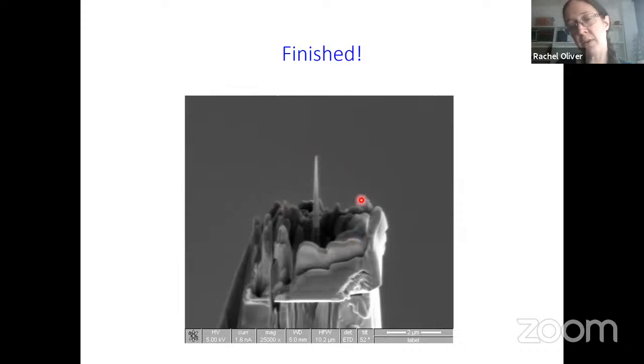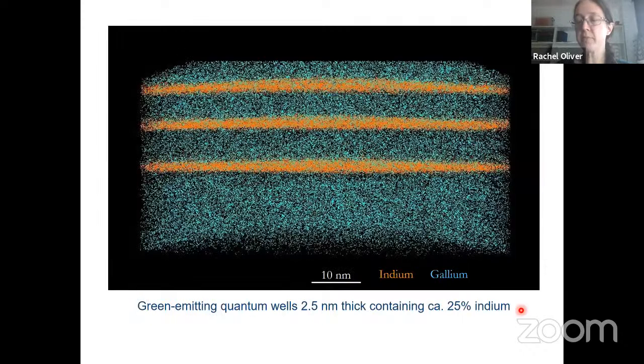So this is actually one of our very first atom probe specimens. And this is what it looks like stuck on the top of a big steel needle. And from that, we can then actually collect an atom probe data set for this indium gallium nitride quantum well sample. This happens to be a green emitter rather than a blue emitter, but you can see the quantum wells here as the orange stripes with the blue gallium nitride material between them.